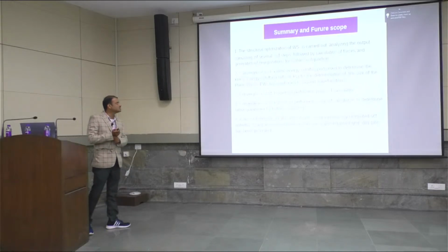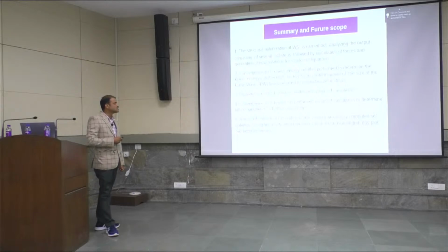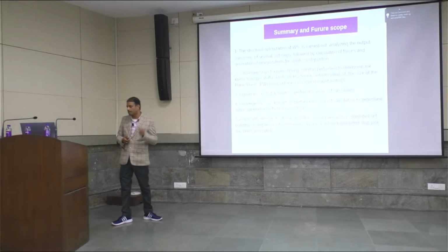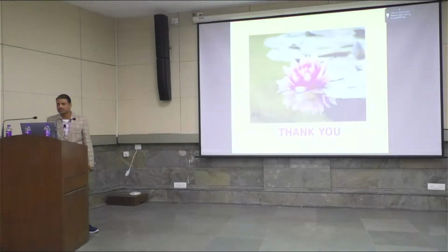In summary, first we have optimized the structure of the molybdenum disulfide by carrying out calculations using the XCrySDen software. Another thing, we performed a convergence study with respect to kinetic energy, and then we performed convergence with respect to K point using SCF calculation, and then we performed a density of states study. And further, our goal is to calculate the band structure by using NSCF. Thank you.